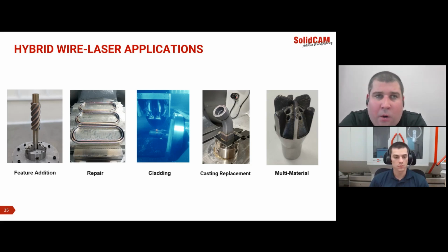But really, a good benefit for hard facing as well. So adding a much higher hardness material where you need it, and using a much cheaper alloy to do the large majority of the print.